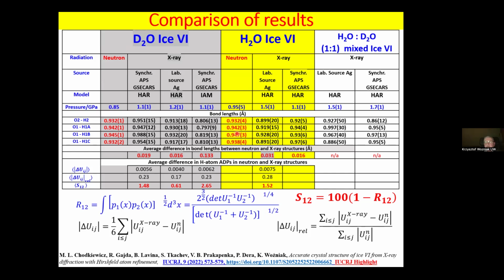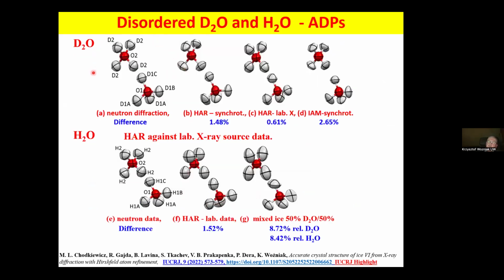anisotropic temperature factors only around 1.5%, 0.6%, 2.6%, and here 1.5%. So here they are. These are the neutron ADP values for hydrogen atoms. And these are ours from different refinements. And in blue, you see the difference expressed in percent.